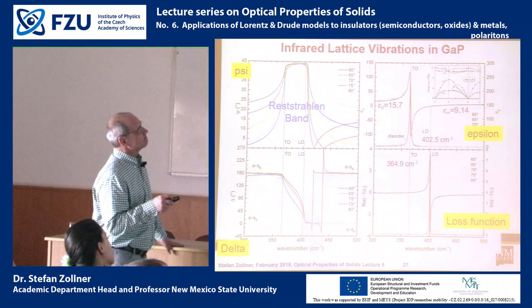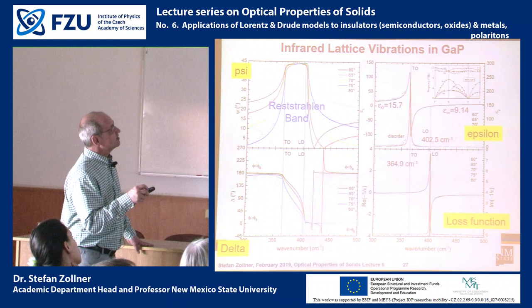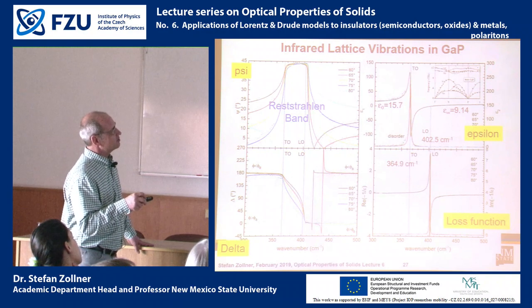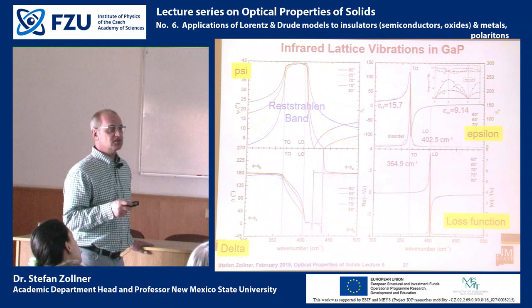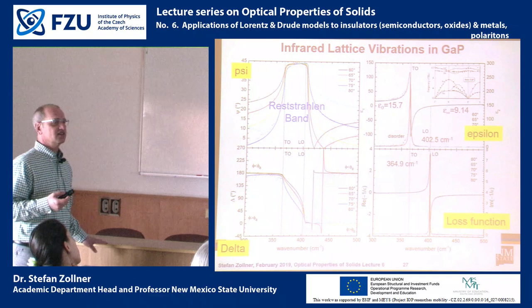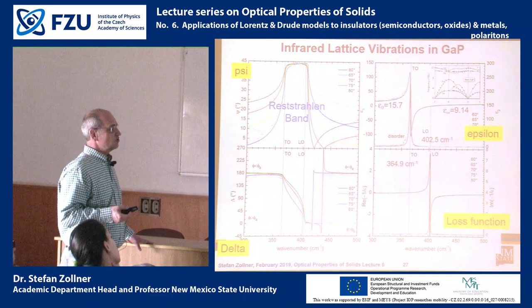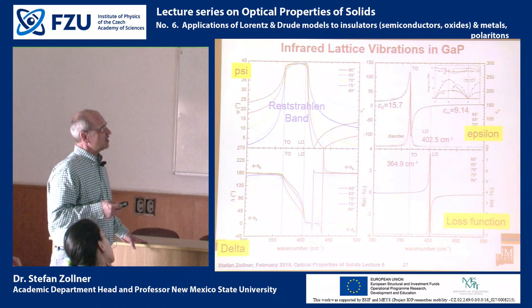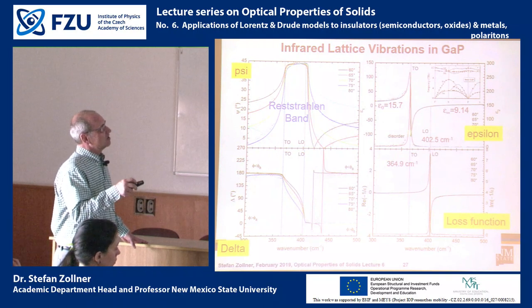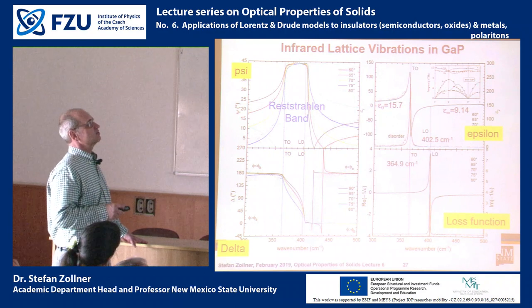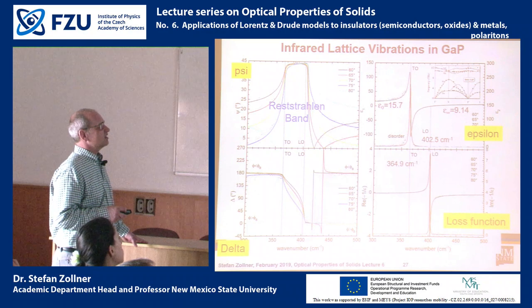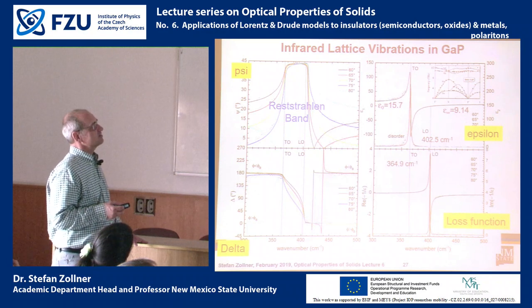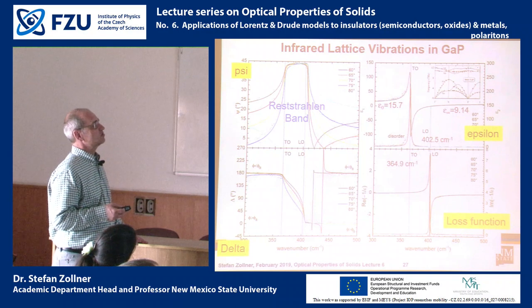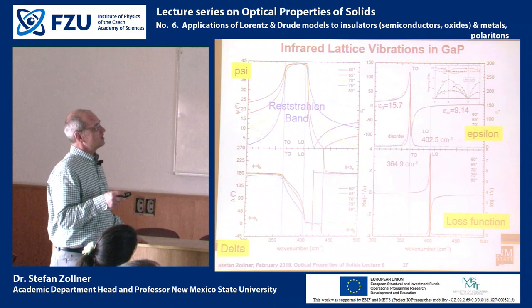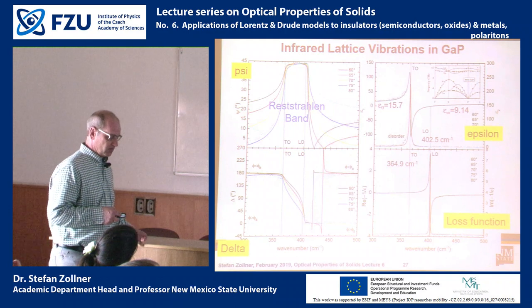In the Lorentz model, the broadening of the peak in the dielectric function is equal to the broadening of the peak in the loss function. That is an assumption which comes from our specific damping model. We're assuming that the friction is proportional to the velocity, and therefore these two broadenings must be equal. But that assumption is not always valid, and therefore for some materials we get a better agreement if we allow two different broadenings for the longitudinal and the transverse modes.